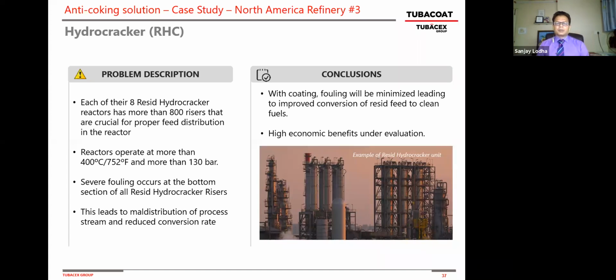And once they have this fouling and the cracking, that leads to the maldistribution, and they're not getting the conversion they would desire. So with the coating, they will be able to minimize this erosion and the fouling, and it is expected to give a far better conversion. Again, this project is for 2021 due to COVID-19, and we'll keep you posted on the benefits that will come out of this trial as well. Next slide.